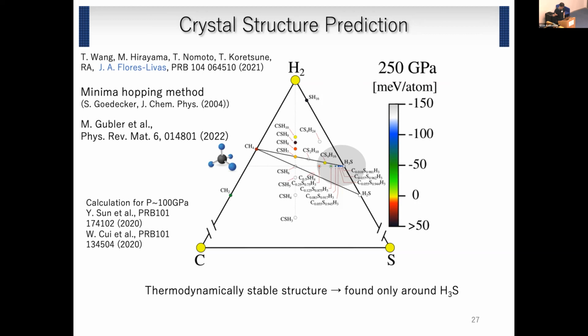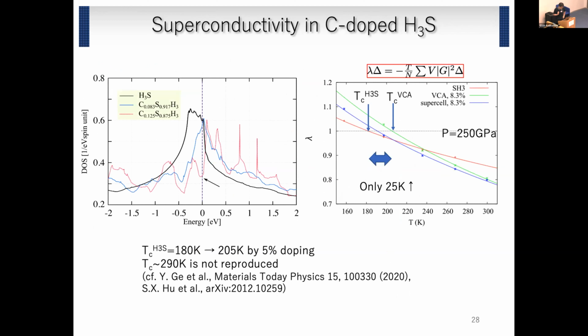So if we calculate thermodynamic stability, then H3S is very stable. And if we introduce carbon, then the system becomes very unstable in general. And we found that only the structures around this H3S are thermodynamically stable. So we decided to study the effect of carbon doping in H3S. If we dope carbon, then the peak in the density of states becomes close to the Fermi level. So this is good for superconductivity.